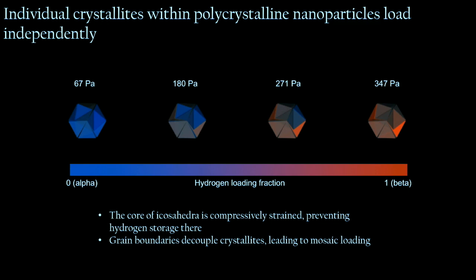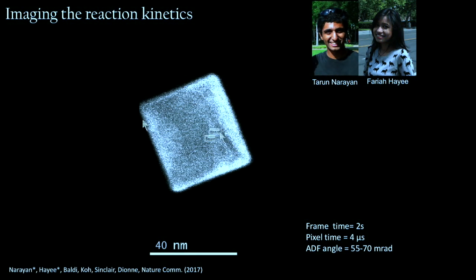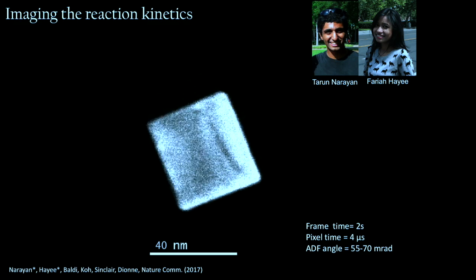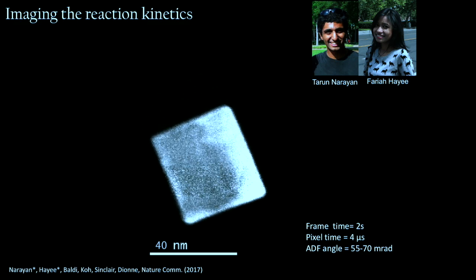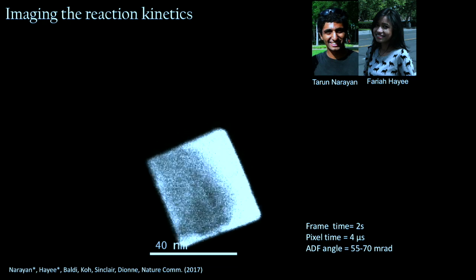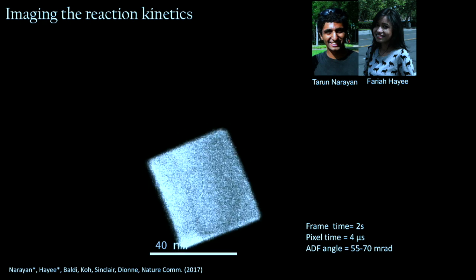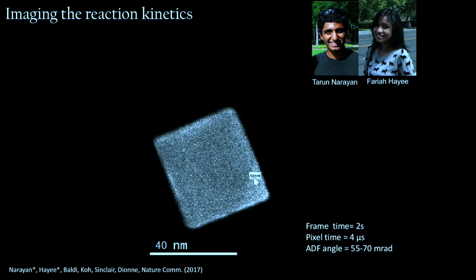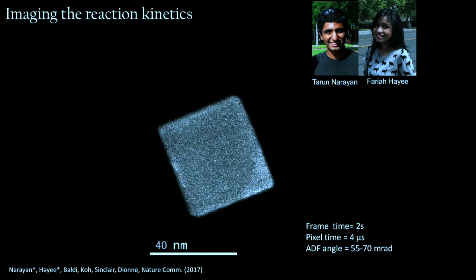Okay, so all of that is in equilibrium, essentially showing that if you want to maximize energy storage, these single crystalline nanoparticles are best. But what happens when we look at kinetics, or what happens dynamically? So here again, we can rely on contrast both in the electron spectra and the diffraction spectra. And you'll notice that part of the cube is turning white. That's where hydrogen is intercalating first from the corners of the nanoparticle. Then you notice it kind of wets the surface and eventually forms a 1-0-0 type interface.